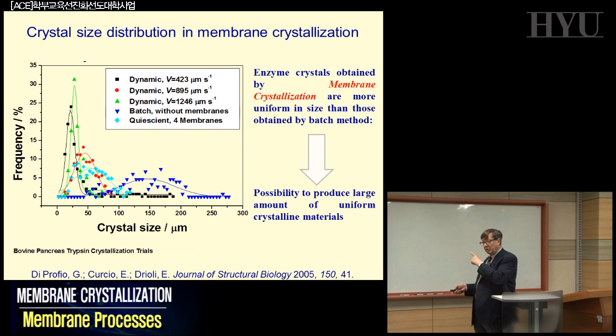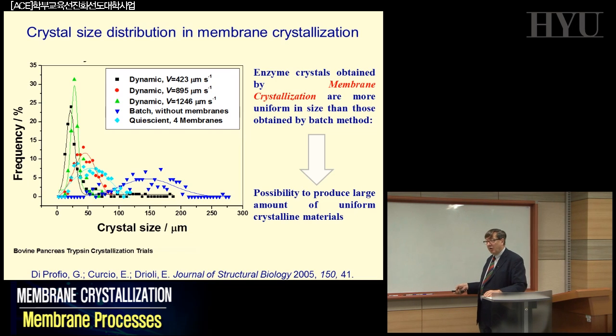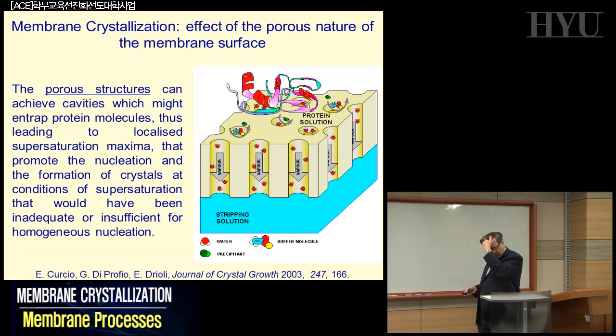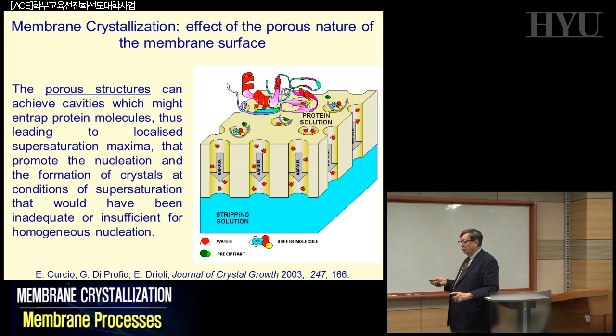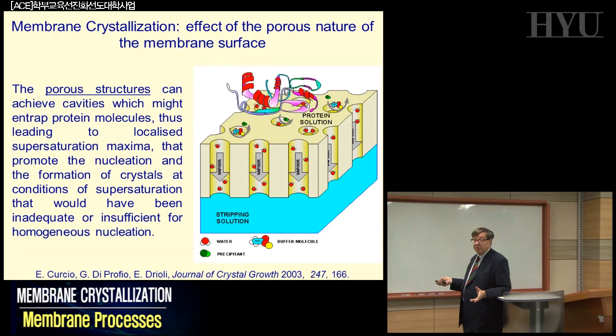And that was related to the assumption that was made and has been verified very early. Enzyme crystals can be obtained in much more uniform size than normally obtained in a batch system, and you have the possibility to produce a large amount of uniform crystal size. That was the conclusion already about 8-9 years ago now in protein crystallization. That was quite interesting. I was starting this story because, as I was mentioning, to crystallize protein is not easy. And in some cases, it was impossible, by the way.